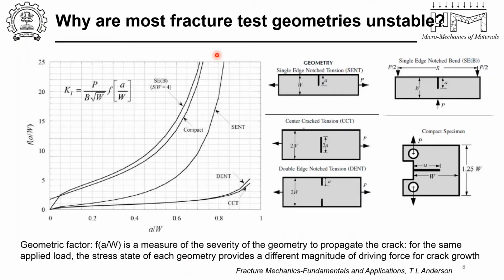Yes, so there are many geometries that are available, and those are listed here. The geometric factor of each of these geometries is plotted as a function of the relative crack length. Relative crack length is a by W. As you can see, if I take an a by W of 0.6, then the geometric factor for a bending configuration, that is a single edge notch bend specimen, is much higher than, let's say, the double edge notch tension or the central crack tension specimen.